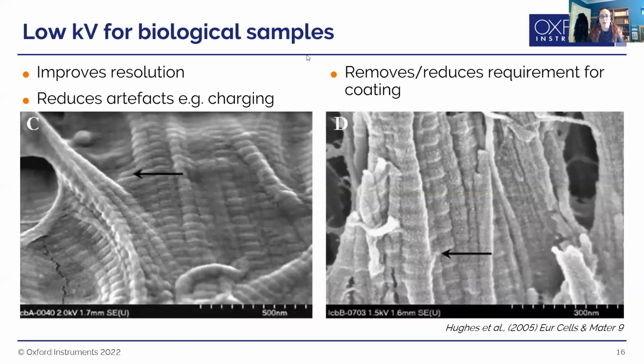Now, low kV for biological samples has been used for quite a long time, and this is for a variety of reasons. It does improve resolution. It also reduces artifacts, such as charging of the sample, and it means you can potentially image samples without coating. Now, these are some electron micrographs I produced many years ago, showing the D-periodic banding